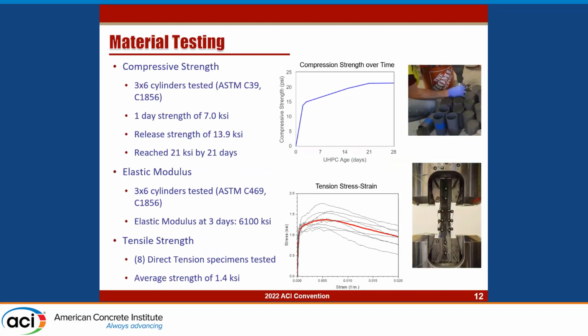And then once we got back from the field, we began our material study. For compressive strength, we tested 3x6 cylinders, which is standard for UHPC. We got a 1 day strength of 7 KSI, and then a release strength of 13.9 KSI. We reached 21 KSI by 21 days. And then after that, it's just been mostly plateauing since then.